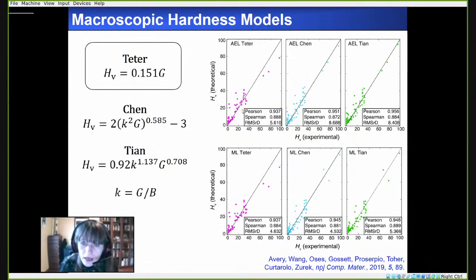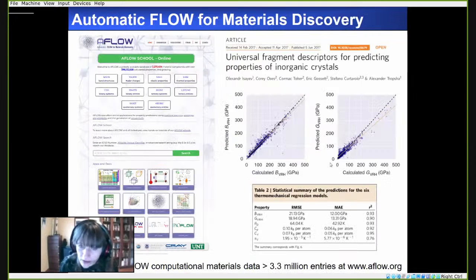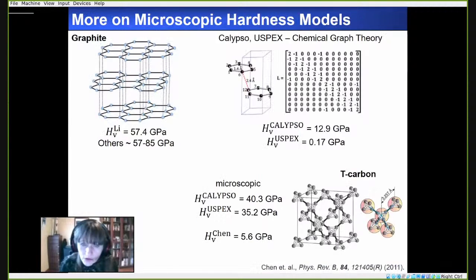So if you look here at the correlation coefficients, here I show experiment versus theory of the AEL, that's the first principles calculations, and the ML, that's the machine learning. Generally speaking, you can't really decide from these correlation coefficients and the root mean square deviations which model is better. However, what we found, if you look here, is that B, in some cases, this is the original AFlow machine learning model, in some cases B is very low. And we also found that the machine learned B, in some cases during the crystal structure prediction search, was way too low.